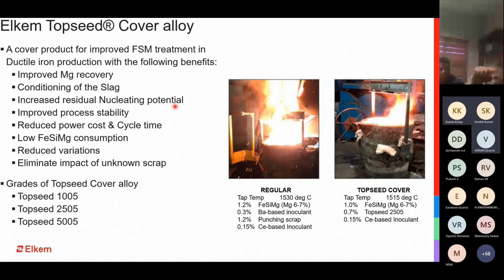You add a known cover, a cover for which you always know the chemical composition, and you add less of it. How does it help you? It improves the recovery of magnesium. It conditions the slag, so that you have dry slag and it does not go into the system, into the molds. It increases the nucleating potential. Definitely, it gives you a much more stable process compared to unknown covering. It reduces the power cost and the cycle time. Of course, we can take it as a separate discussion. How does Topseed help us achieve all this?